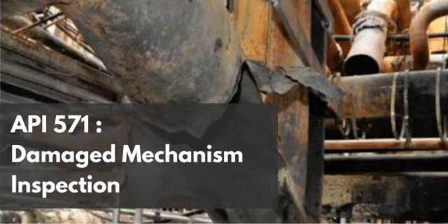Which means the metal directly underneath that specific lump of coke is going to carburize and turn brittle much faster than the clean, unfouled sections of the tube right next to it. You get a hot spot of damage. Right, you're getting localized, highly concentrated degradation. Precisely. It creates a severely weakened, brittle spot in a tube that is already operating under extreme internal pressure and extreme thermal stress. It is a ticking time bomb.